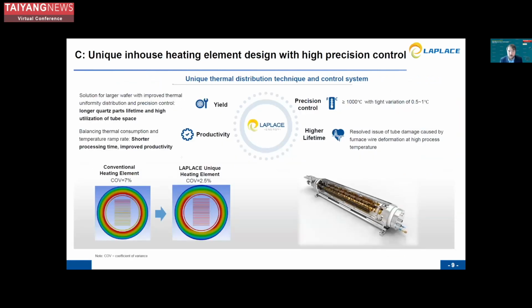The other point that I want to mention is the heating element. And here we talk again about getting uniformity over large batches. This also in return increases the quartz lifetimes and the utilization space of the tube. And thanks to a better control of different elements within the tube, we can also use shorter process times and therefore get the productivity up.